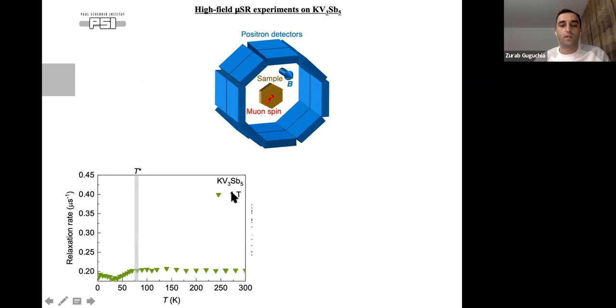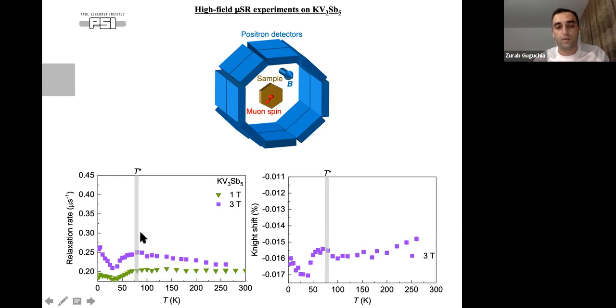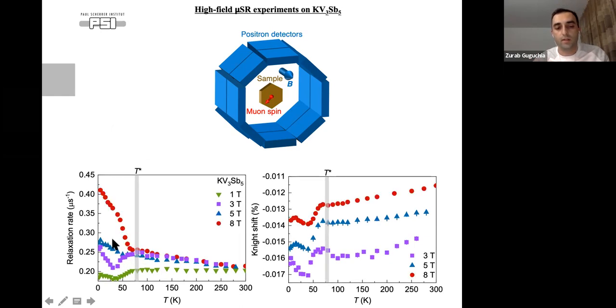So here what we see in 1 Tesla, you see that we have this kind of non-monotonous behavior. In high field, we cannot distinguish between electronic and nuclear contribution. This is similar to the behavior we observe in zero field, but for nuclear moments. That's why what we're seeing is mostly dominated by the nuclear moments. But when we increase the field, then we see a stronger, clear increase at lower temperatures, and we continue to 5 Tesla, again a bigger increase, and at 8 Tesla we have a very well pronounced increase of the relaxation rate at low temperatures.